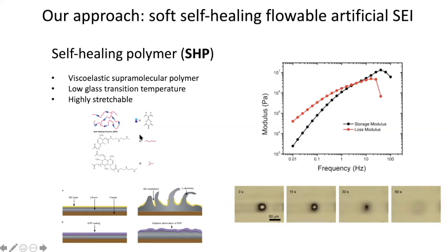it's very soft, it's in contrary to the concept that people have been using before, using tough polymer. Here, we use a very soft polymer. But the thing is, this polymer has the unique property. If you look at the microscope image here, if we poke a hole on the polymer, after 30 seconds, 60 seconds, this hole essentially heals by itself.